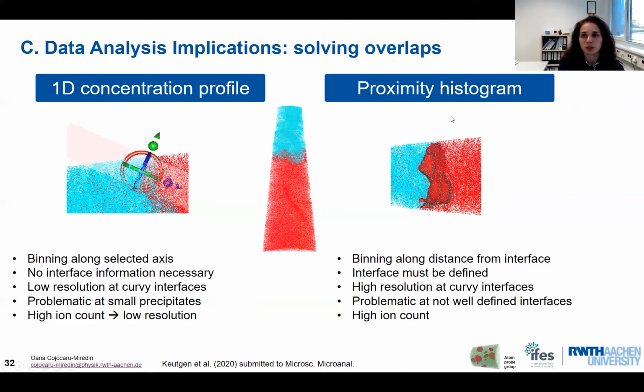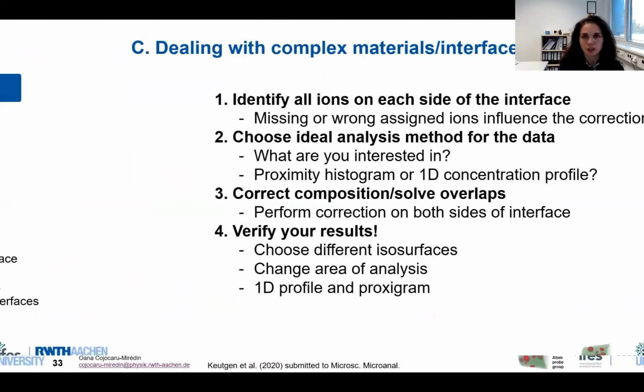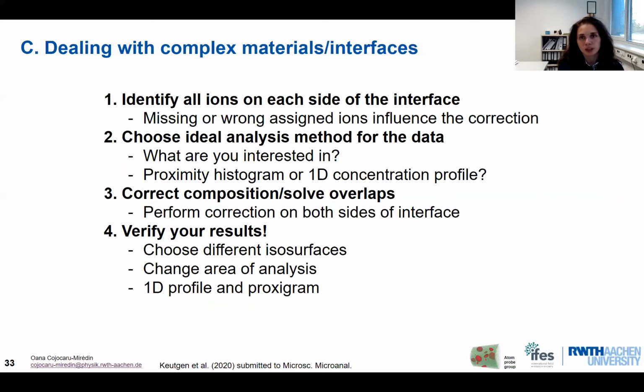The disadvantage of the proximity histogram is that the value that we get is always dependent on the isosurface that we have generated at the interface. So we always need to be very careful when we deal with the generation of the isosurfaces. So when we deal with complex materials and interfaces, we need to perform 4 important steps. First of all, we need to identify all ions on each side of the interface. Of course, if we miss some ions or wrongly assign some ions on either side of the interface, then we will no longer have a very robust result.